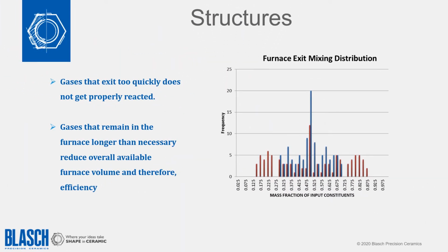This graph will show in blue a VectorWall distribution. You'll note that the highest frequency of perfect residence time is dead center, and the distribution on either side of that is quite tight. The reason for that is because as the gas passes through the wall and begins to rotate, it creates something called a plug flow. So that type of rotation and flow causes the gas front, if you will, to move very consistently downstream. Everything that's in that rotation is traveling the same length. They are going the same distance to the exit. You get a relatively tight, narrow distribution of your residence time.